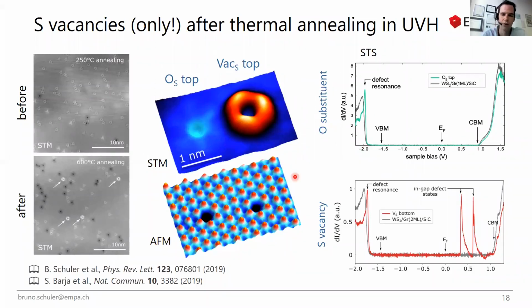And then if you look at the same spectroscopy at a site which we now know is a vacancy, and these things really only appear after you anneal them to quite high temperature, a few hundred degrees in vacuum, you see these two very clear defect resonances, which are followed by some vibronic sidebands. We know from the modeling that this is 100% consistent with the presence of vacancies. So that means if you anneal it in UHV at high temperature, you can selectively create sulfur vacancies.